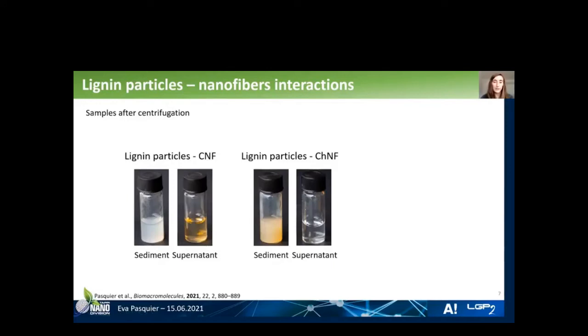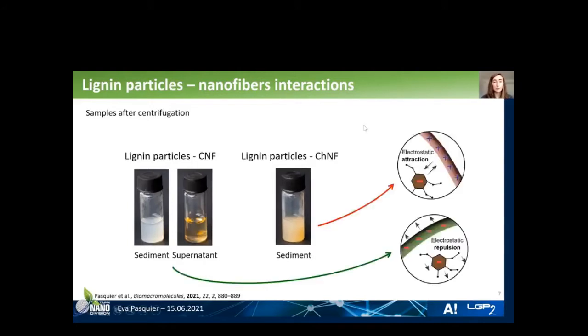And for the chitin nanofibers and lignin particles, the lignin particles were present in the sediment with the chitin nanofibers. This is because we have electrostatic interactions between the lignin particles that are negatively charged and the chitin nanofibers that are positively charged. While for the cellulose, we have both components that are negatively charged, and this leads to electrostatic repulsion. So we kept the lignin particles and chitin nanofibers because we want to have good adhesion during the film making process so that we do not lose any lignin particles.